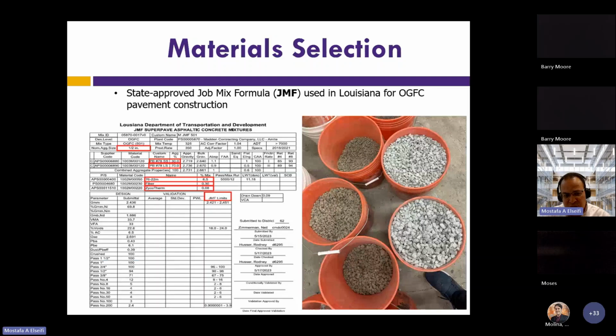So the mix that we used was provided by the Louisiana Department of Transportation and Development. This is a mix that is actually approved by the department, and it has been used in roads. So it's a mix that, again, has been designed and has been approved. Some of the features that I'm highlighting in red: the nominal maximum aggregate size is 12.5, which is what we use currently in the state. We have two sources of aggregate, so it's a very simple mix design, but it meets the specification.